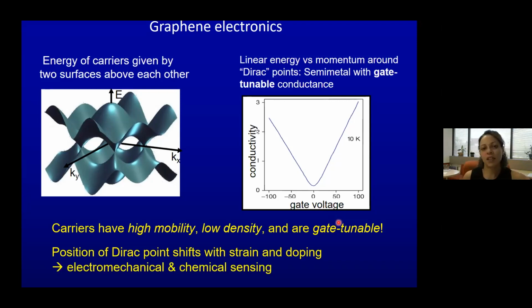the mobility isn't very high. It's not ballistic. You get a lot of scattering in these materials. And so graphene bridges this gap by being both gate tunable and high mobility. You also have these Dirac points, which can shift depending on what you do to them. So if you dope graphene or strain it, and by doping, I mean you apply electrostatic doping, or generally if you put a chemical on it that adds carriers to the graphene, the Dirac point will shift. So then automatically graphene becomes a really interesting electromechanical and chemical sensor just by moving that Dirac point around. And that's the basis of a lot of graphene sensing devices.